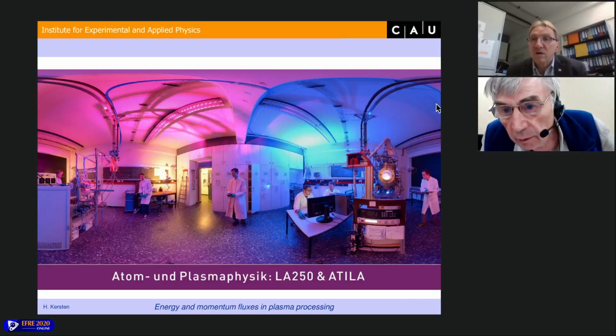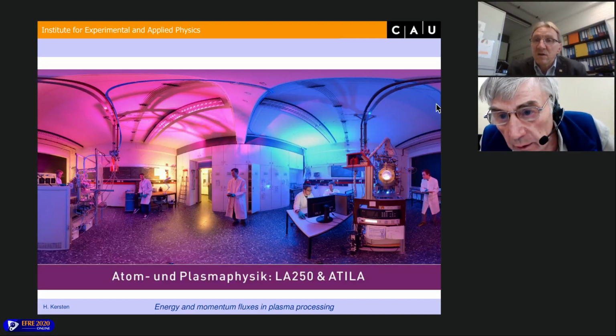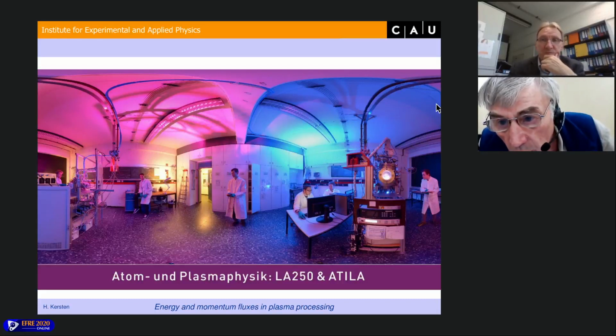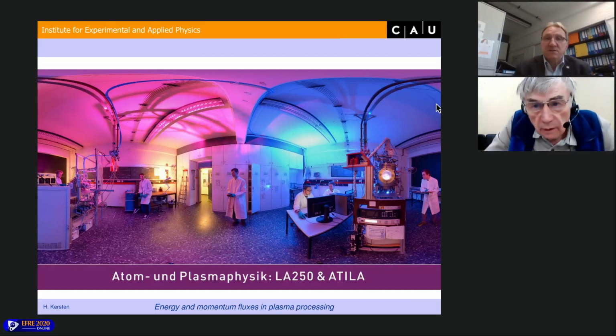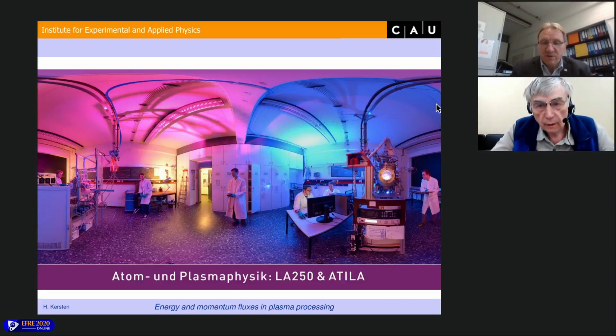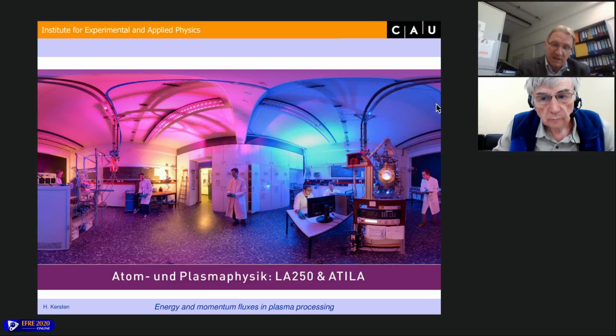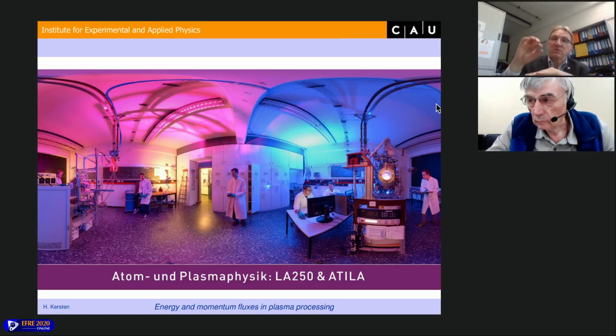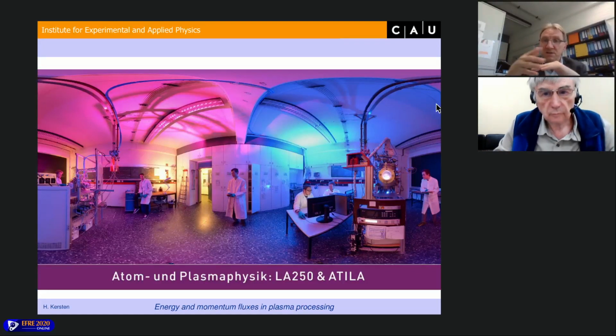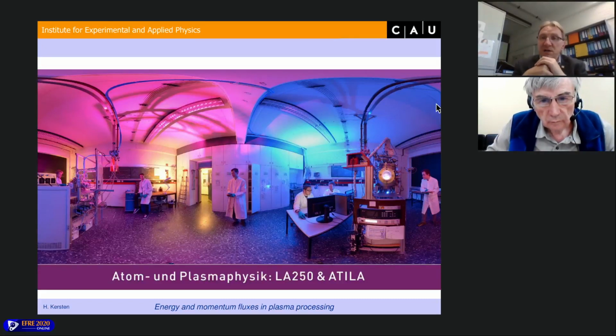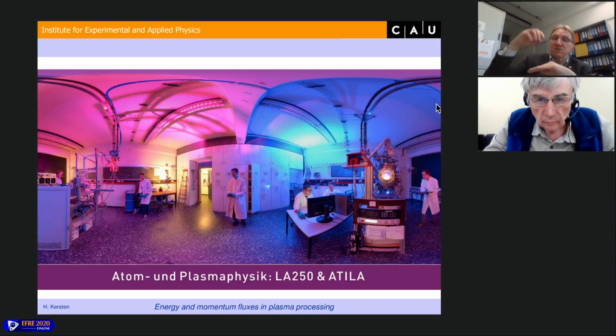Do you see, at the beginning of your talk about carbon structures, I am interested why nickel dots were used for the carbon structures. Yeah, this is just what was used. You know, if you want to grow, for instance, carbon nanotubes in an acetylene or methane plasma, you need a kind of a catalyst or a footprint. Often iron is taken, but also nickel can be taken as a catalyst at the substrate where the carbon nanotubes are growing on this catalyst, on the nickel in this case. And we use that also for the growth of our carbon structures, of our carbon pillars. So it is just a catalyst where the structures start to grow.